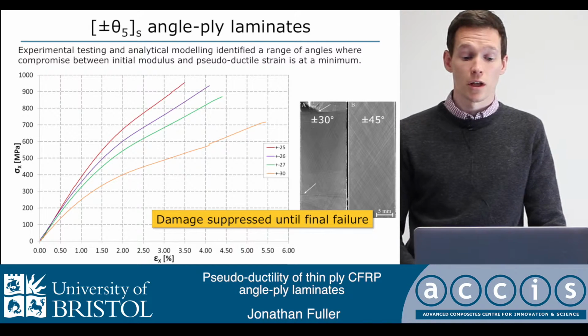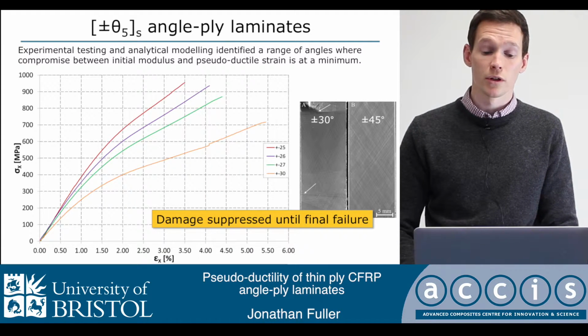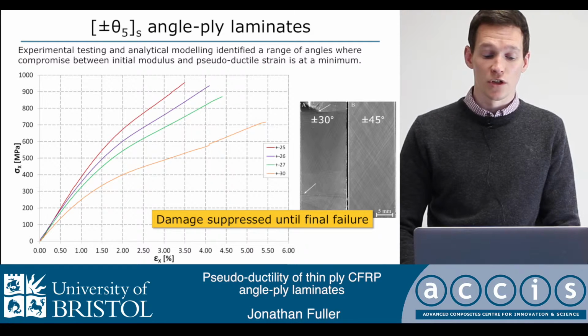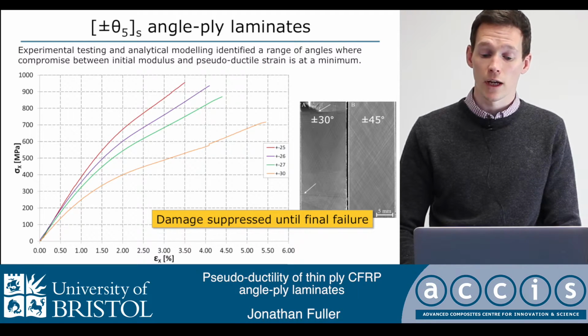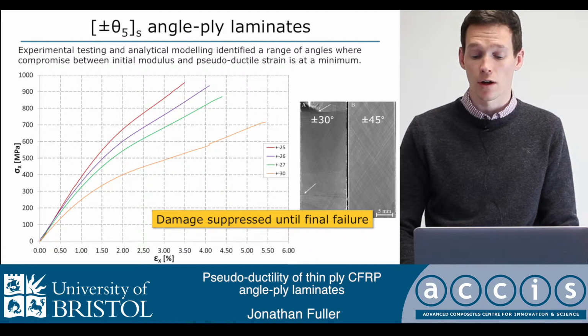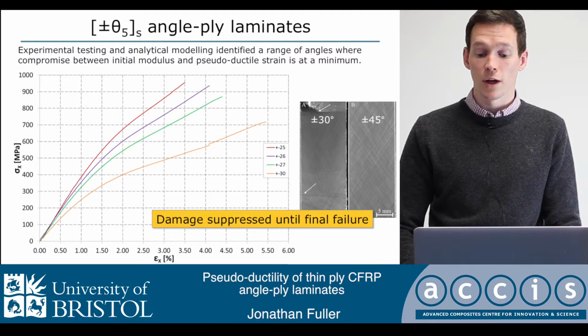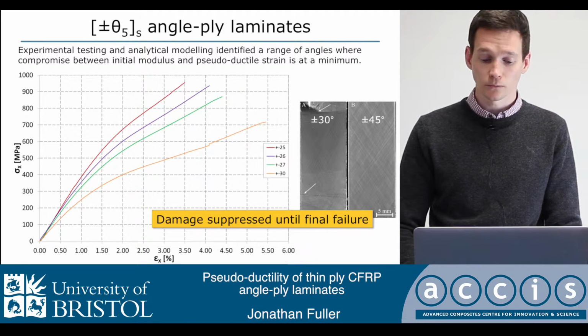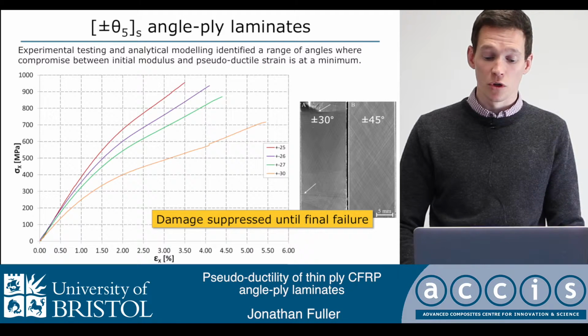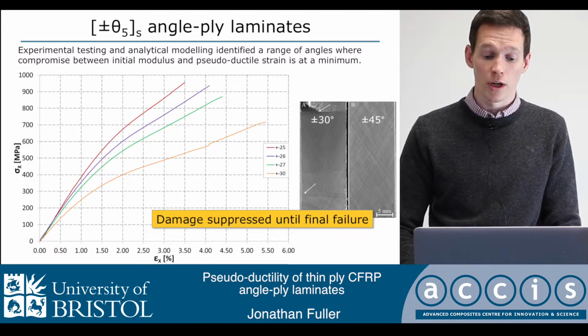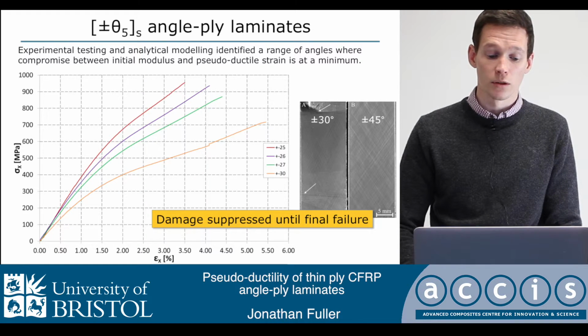So experimental testing and then analytical modeling showed that it is possible to do this with this material using a plus or minus theta symmetrical configuration. So in the graph there's 25, 26, 27 and 30 from left to right shown, and then CT images on the right hand side of a plus or minus 30 and plus or minus 45, both showing that at failure there's absolutely no large scale damage in the specimens, which told us that this concept does actually provide the results that we wanted.